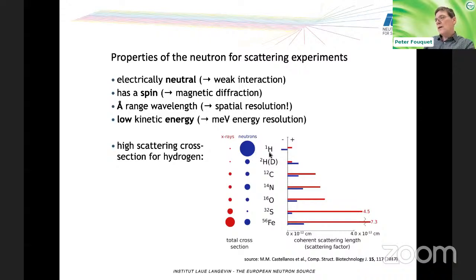And you can also play, using quantum mechanics, some other tricks. You have actually a negative so-called scattering length for hydrogen. And this means that if you have the right mixture of hydrogen and deuterium, which is the variant of hydrogen with 1 neutron more, then you can reduce contrast, or you can pronounce certain parts of a hydrogen sample, and change contrast in your sample and make some parts of, for example, polymer assemblies visible and others disappear. It's used in this research, for example, with small angle scattering that Sarah showed.